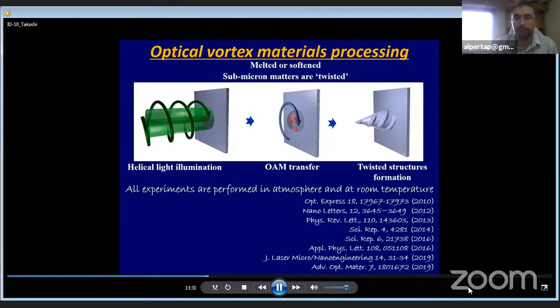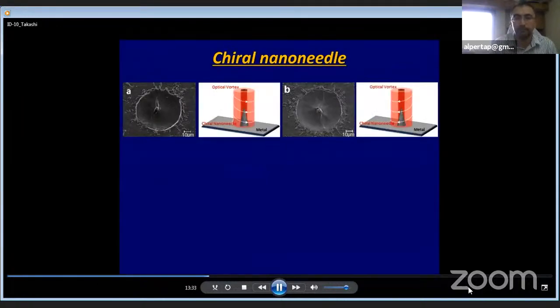First demonstration: 2010, already 10 years back, we found that tantalum, a metal, when irradiated by an optical vortex nanosecond pulse, shows this image of the surface of the irradiated target. You can find some small needle-like structures here on the dark gold target. I would like to show you a zoomed-up image of this tiny needle.